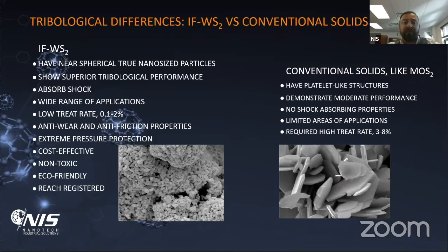It has a wide range of applications because the particles are small and dispersion is much easier than a regular micron-sized particle of molybdenum disulfide or tungsten disulfide. Thus, applications are not limited only to grease, as with molybdenum disulfide, or primarily to grease. We also use them in metalworking fluids, in oil, industrial oils, automotive oils, and coatings as well. The treat rate is low, because the size is very small, and the smaller the size, the higher the surface area, and the treat rate goes down. So we observe treat rates from 0.05% up to 2%. They have excellent anti-wear and anti-friction properties, phenomenal extreme pressure protection, and I'm going to show several slides on that. It's cost-effective, non-toxic, eco-friendly, and REACH registered.